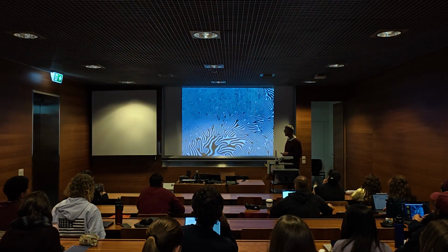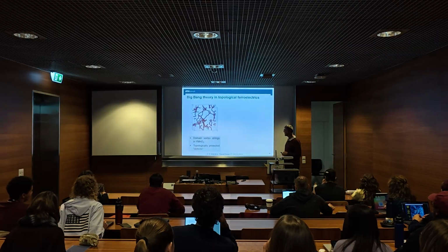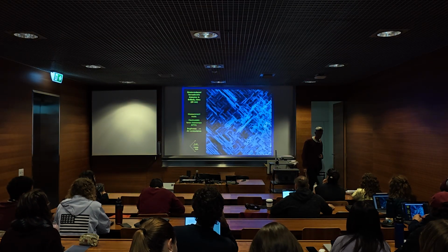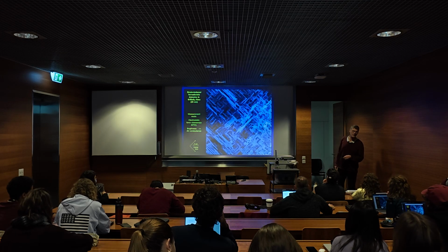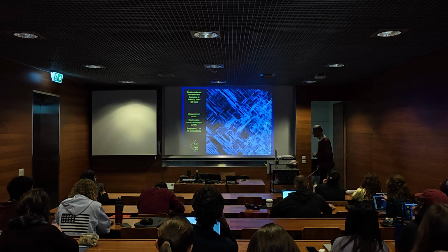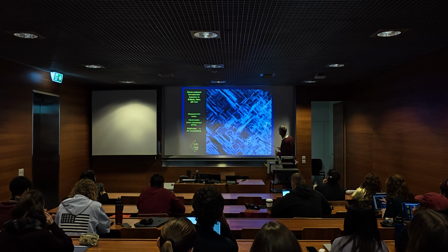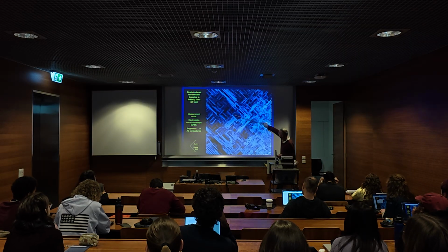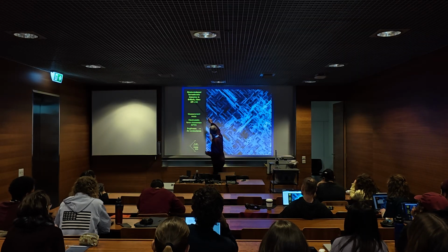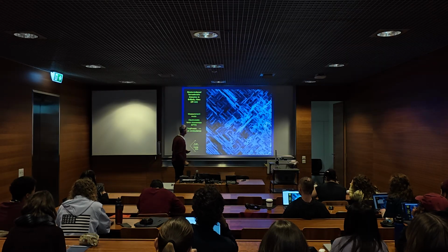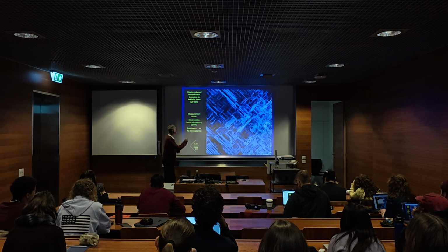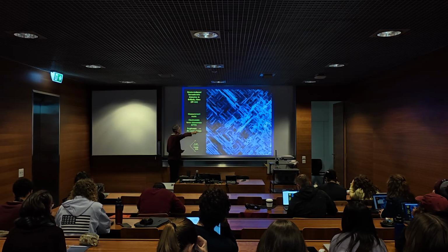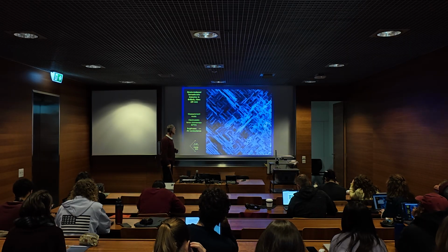So this one, and also that one, we measured in our lab, not for the science, but we wanted to test our piezoresponse force microscope. And then we did this, and then we said, oh wow, this looks beautiful. So that's what you get when you look at strained EuTiO3 films, which are also ferroelectric. The strain makes the film ferroelectric, and then you have very small domains, 20 nanometer size, in a